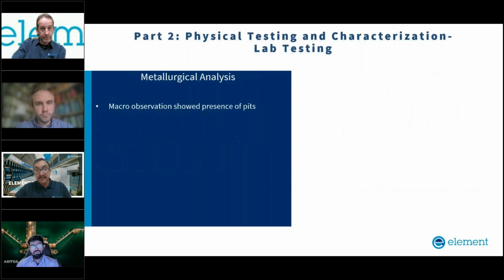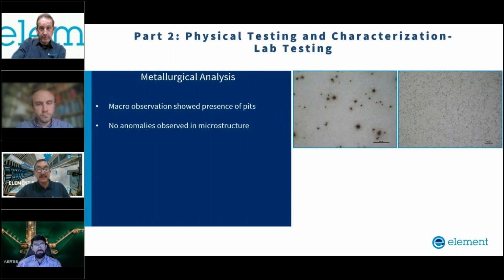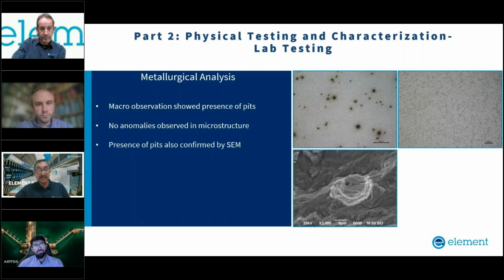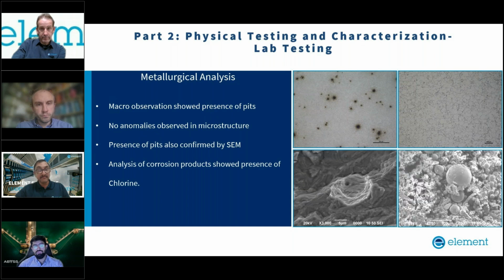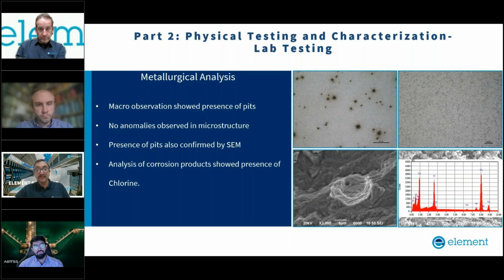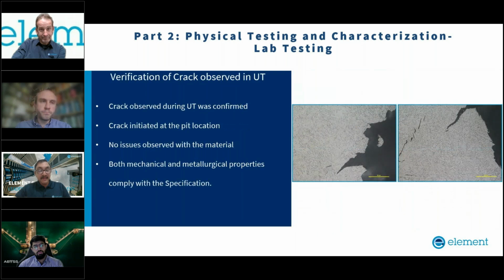For the cutout sample, which we are showing in the next slide, we have done macro and micro observation. Again, there was no anomaly in the microstructure found, but we observed the presence of pits. We have done further analysis in the electron microscope, which shows the presence of pits, and we have done EDS analysis, which shows the presence of chlorine. This confirms seawater pitting corrosion on the pipe. Overall, analysis suggested that the material has undergone pitting corrosion, likely due to exposure to the chlorinated environment.